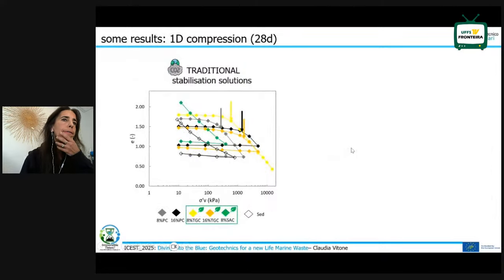So these are the first results of oedometer tests in the void ratio versus vertical effective stress plot. Here you can see the natural sediment. And you can see here the result of the mixtures, just the control mixtures. So these are sediments and cement, different cements. In yellow is the steel slag, in gray and black the Portland, and in green the sulfoaluminate.